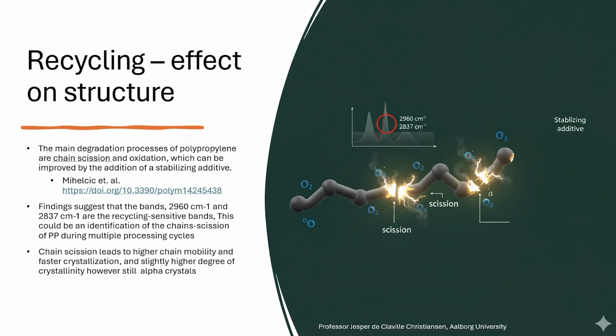When we recycle a polypropylene, we affect the structure. What happens with the polypropylene is that you cut the chains. So the thermal stress causes a bond to break, and then you have a free radical that will react with typically one of the antioxidants or the stabilizers. If you have IR spectroscopy, there are some bands that are sensitive to degradation. So you can get a measure of the degradation by using spectroscopy.